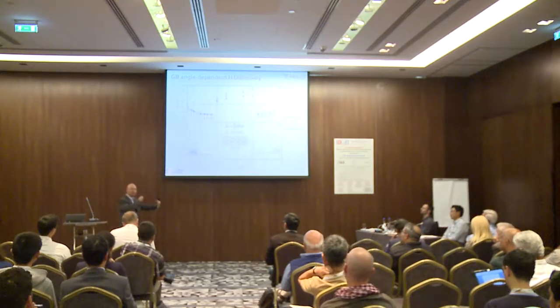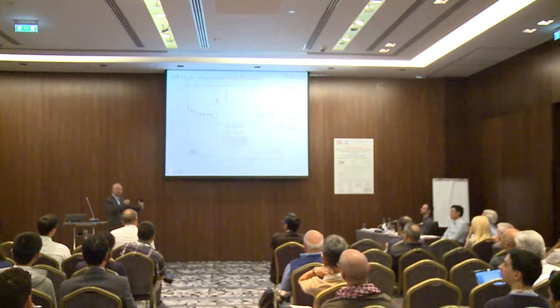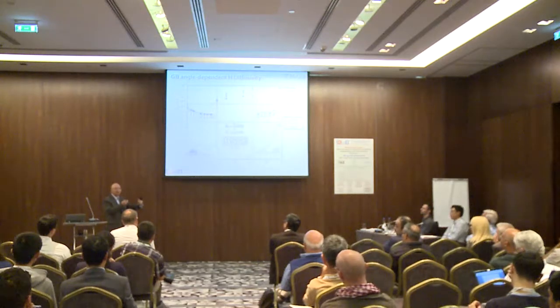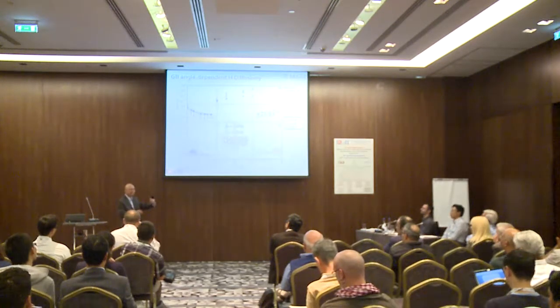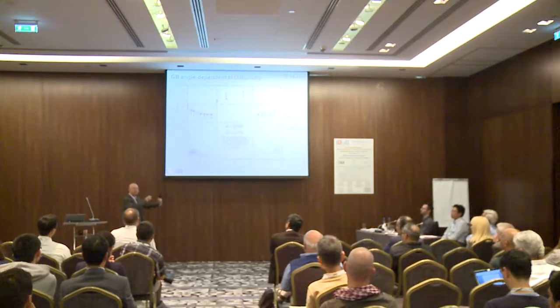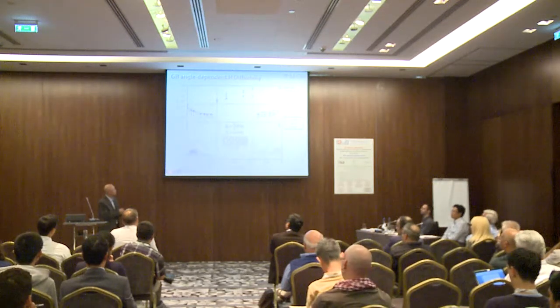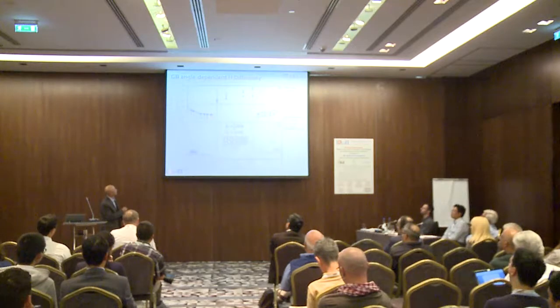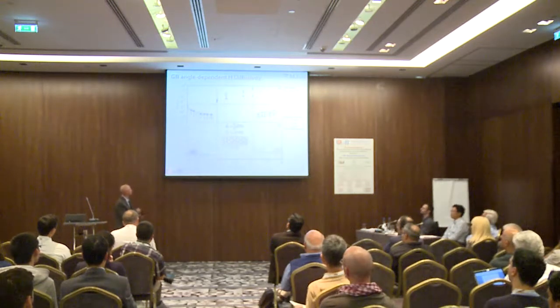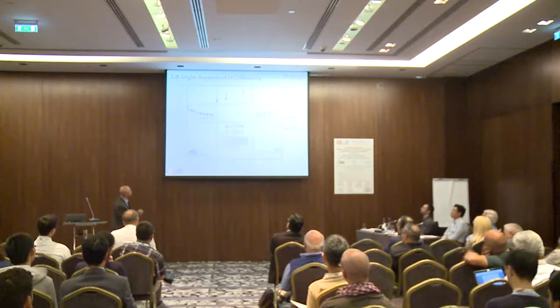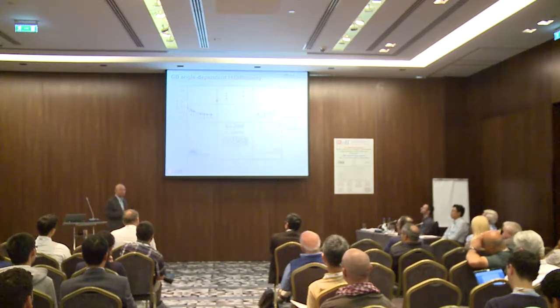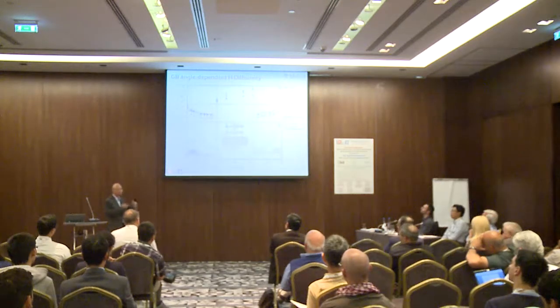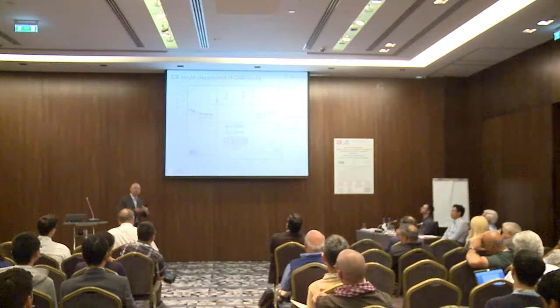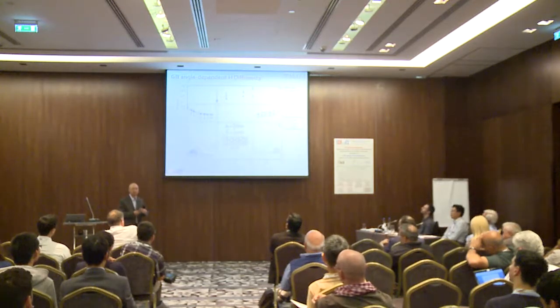But when you're measuring in experiments for the permeation test, well, I'm not an expert, but I know one way is that you take the transient region and you get the effective diffusivity. That's more or less the integration of diffusivity from different concentrations. And you can see from this picture that the diffusivity is really concentration dependent. So you need to take some caution when you directly use the result to interpret fast or slow diffusion from experimental measurement.